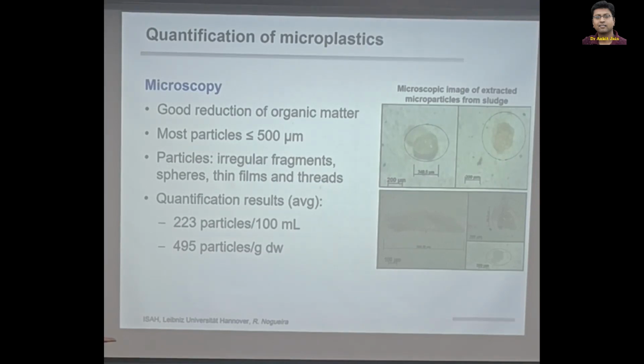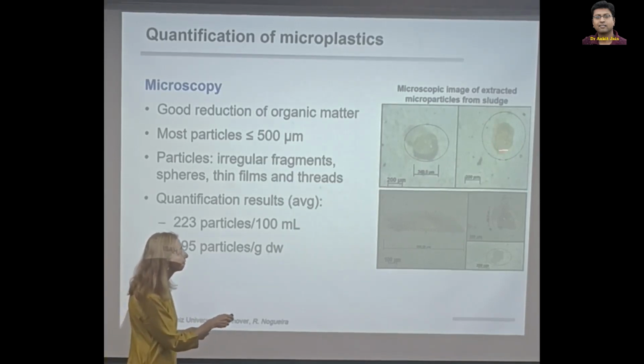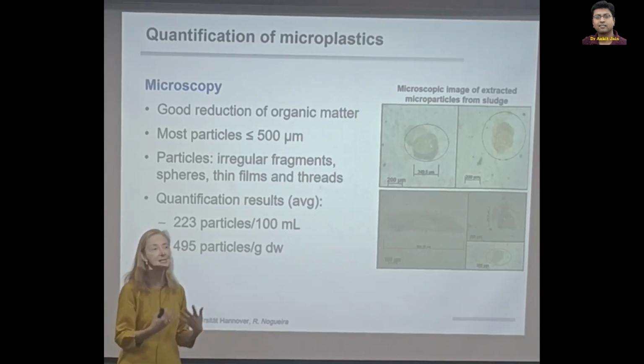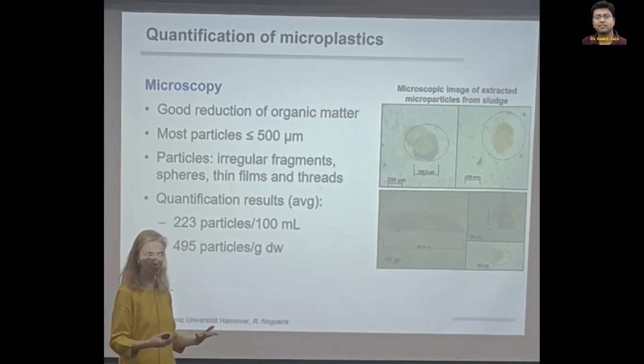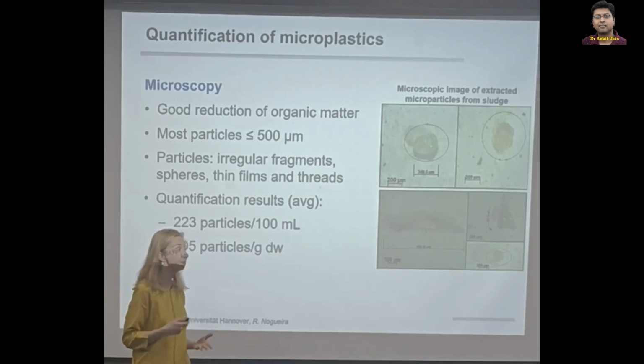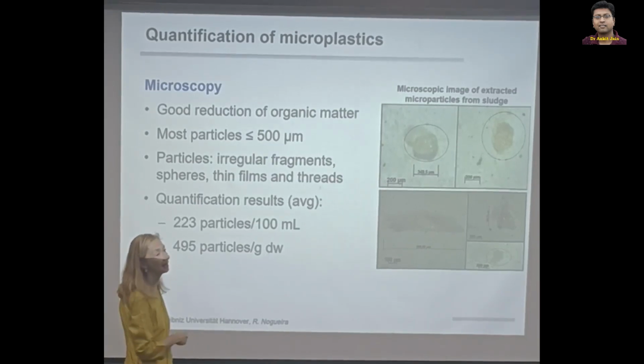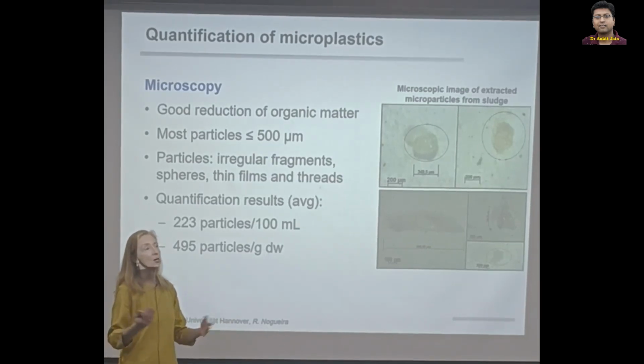Then we observed, because we wanted to control did we clean well the plastics, and we made a microscopy. As you see here, we can very well find our plastics. It means our cleaning process was good. And also with the microscopy, we could count how many plastic particles we have, and we could measure the diameter or the equivalent length of each plastic. And at the end, our quantification told us, for example, this is one of the results, that we have these particles per 100 milliliters of sludge.